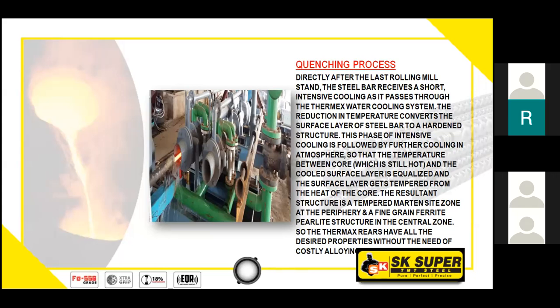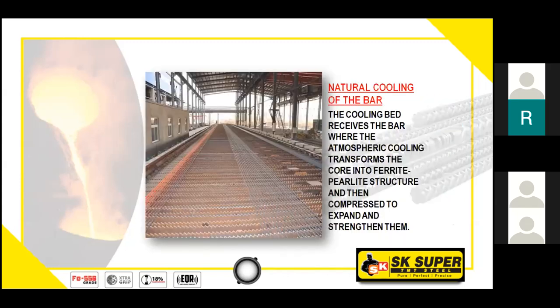It comes out within a fraction of a second, and within a fraction of a second, the temperature of the bar drops from 950 degrees to 500 degrees. Now here, the water pressure and the speed of the bar play a major role, like I told you earlier. Once it comes out of the quenching box, these bars go on a cooling bed.